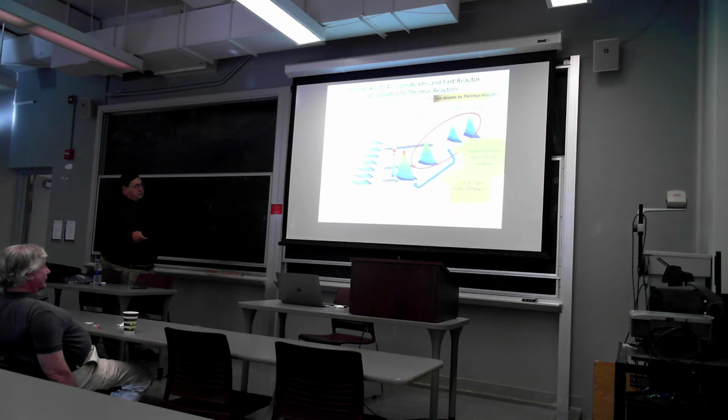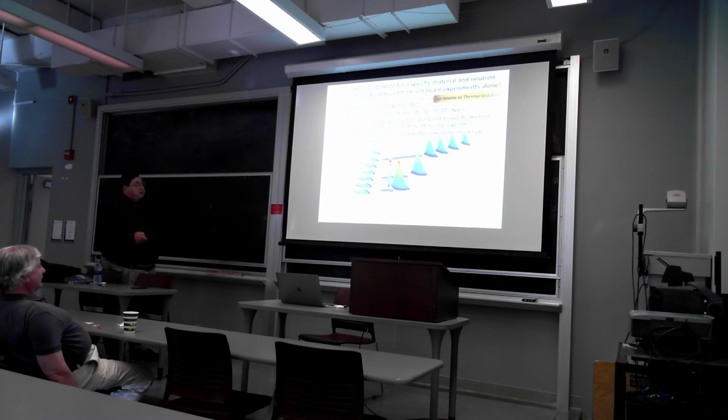in the Russian thermal reactor. But the problem here is the fast reactor irradiations that we use to generate this data point required about 8 years of irradiation. And if you remember, what I said is, if we had enough good data over a wide enough range, that range being about 10 to the minus 4 to 10 to the minus 2 dpa per second, we should be able to actually generate an equation and be able to sort of skip, at least initially, the